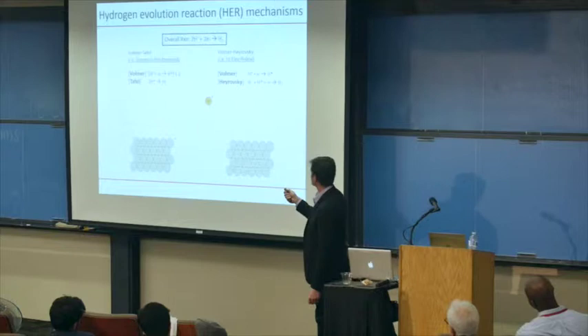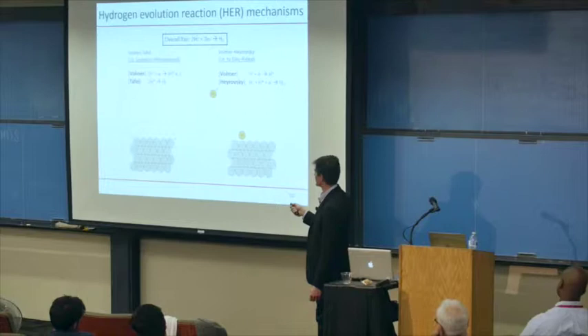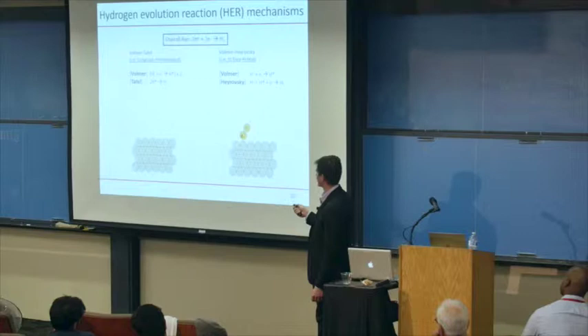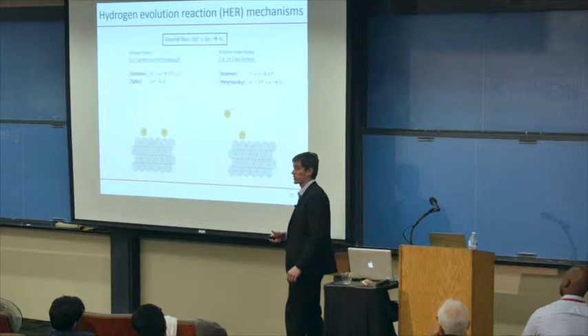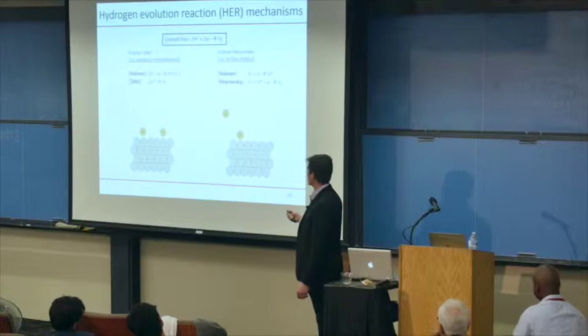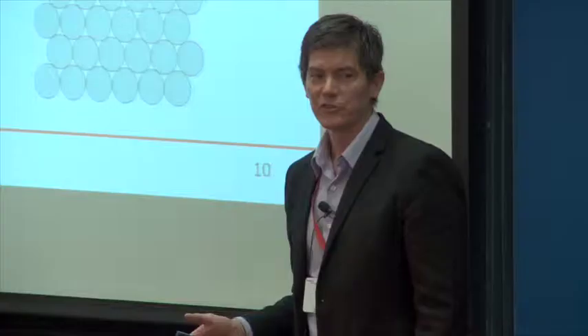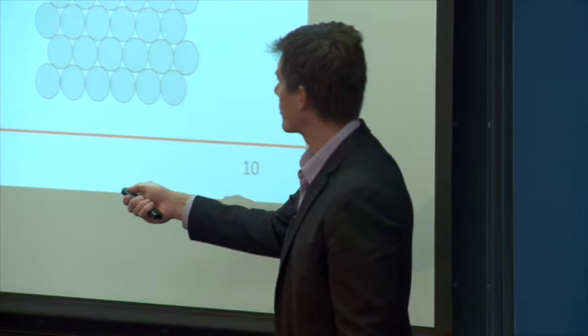The Volmer-Heyrovsky process starts exactly the same way with this Volmer step. The proton comes down, you make an adsorbed hydrogen atom. And now this one, instead of finding an empty site, lands right on top of the first one, gets an electron, and now you make the H2 bond and it takes off. We have no idea which one actually happens in real life. However, there's an interesting point: either way you go, you have exactly the same reactive intermediate sitting on the surface, an adsorbed hydrogen atom. So you might think, well, if I want to make a good catalyst, I want a catalyst that binds this hydrogen not too strongly and not too weakly to let this reaction proceed.